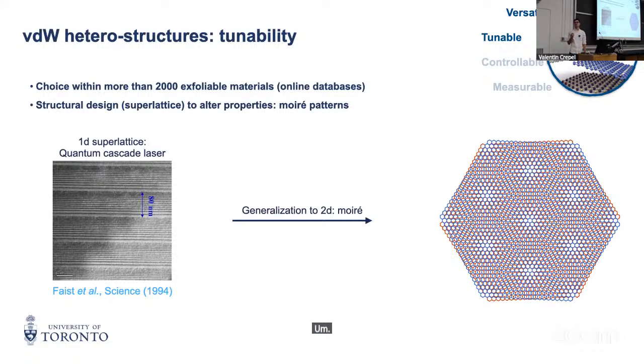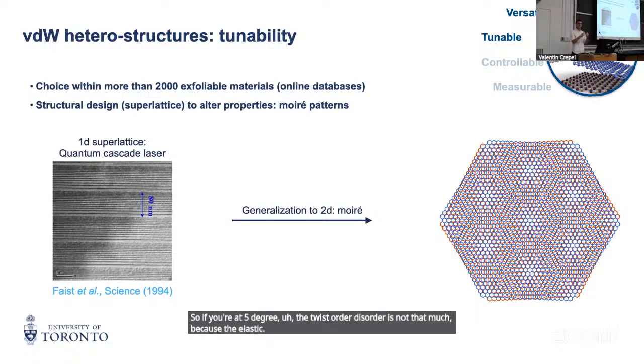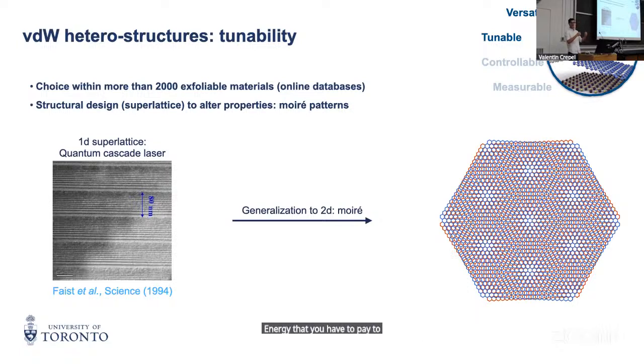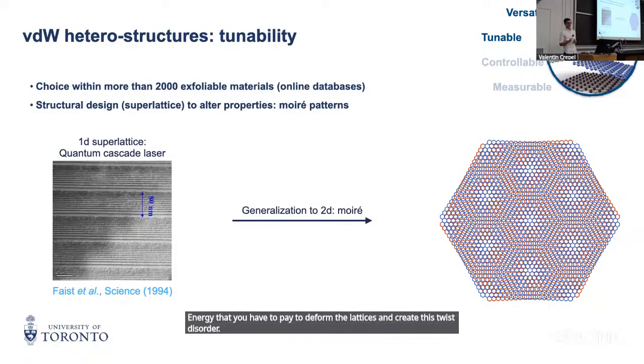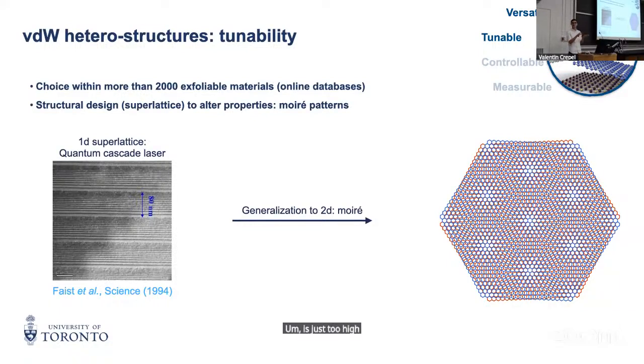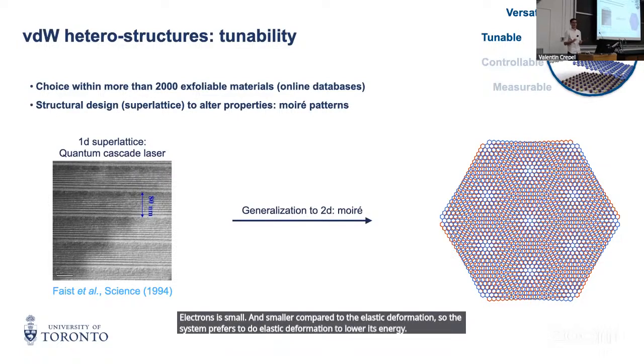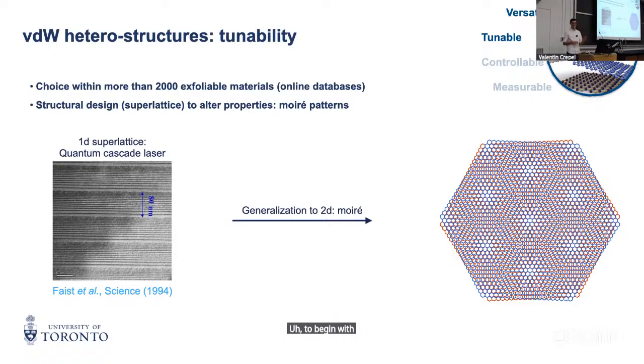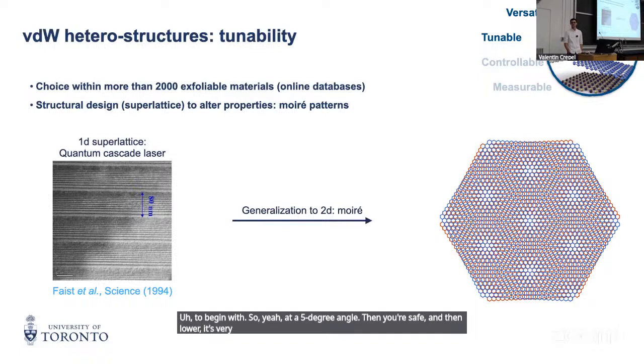And that can change the physics, but that happens typically at lower angle. So if you are at 5 degrees, the twist disorder is not that much because the elastic energy that you have to pay to deform the lattices and create this twist disorder is just too high. At low angle, the kinetic energy of the electrons is small compared to the elastic deformation. So the system prefers to do elastic deformation to lower its energy to begin with. So at a 5 degree angle, you're safe, and lower than that, it's very hard to model theoretically.